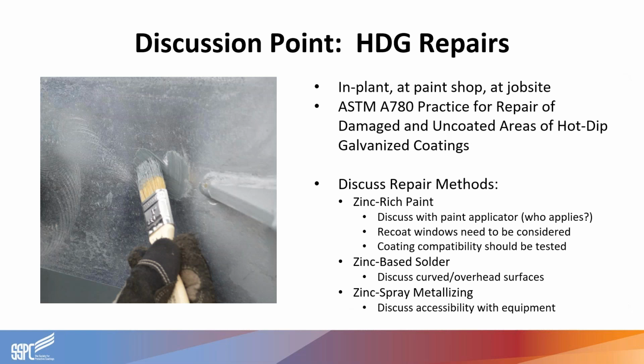The next discussion point between parties would be galvanizing repairs. This topic is not specifically addressed in any surface preparation standard for paint or powder coating, but the acceptability and responsibility for any repairs is definitely worth discussion for a variety of reasons. Galvanizers are actually required to deliver the galvanized product with full coverage, but some repairs are allowable to be performed at the plant, and they must be performed prior to acceptance.